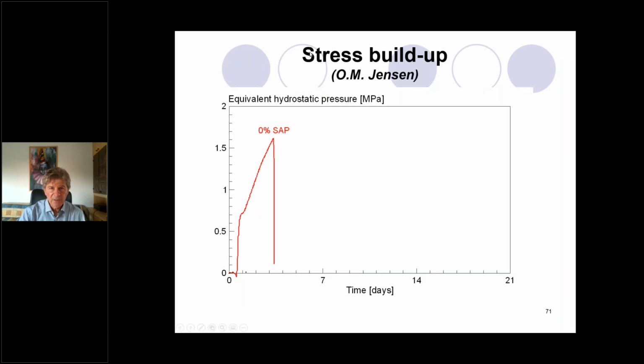This is the stress build-up, illustrating the rise of the stresses in this ring when we have reference concrete, which doesn't contain any superabsorbent polymer, and this sudden drop of the stress says that we have a crack. We have a liberation of the stresses, and we can see it nicely after this drop. So the system is completely automatic, so we can measure automatically.